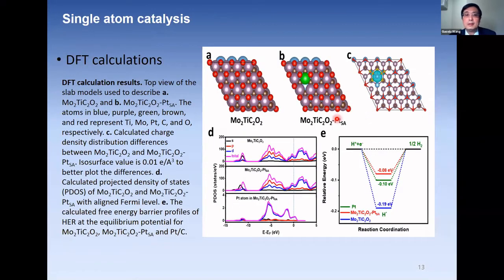And then we did DFT calculations. We found the hydrogen adsorption energy on the surface of Pt single atom on the surface of MXene is lower than commercial platinum carbon catalyst. That explained why the single atom Pt on the surface of MXene can exhibit better HER performance.